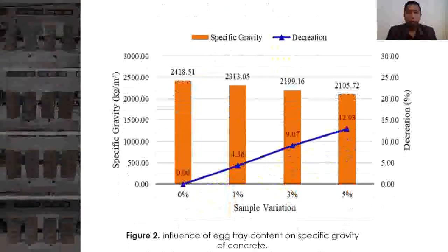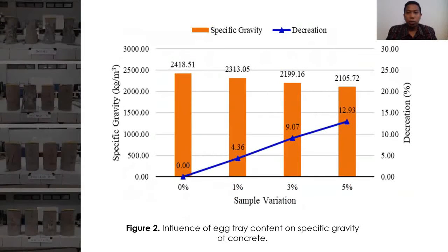The partial substitution of fine aggregate with X-ray can reduce the density of the concrete, shown in figure 2. Based on the sample specimen, normal concrete has an average density of 2,403.47 kg per cubic meter. The replacement of sand with a percentage variation of 1%, 3%, and 5% X-ray results in a concrete density of 2,313.05 kg per cubic meter, 2,199 kg per cubic meter, and 2,105.72 kg per cubic meter.